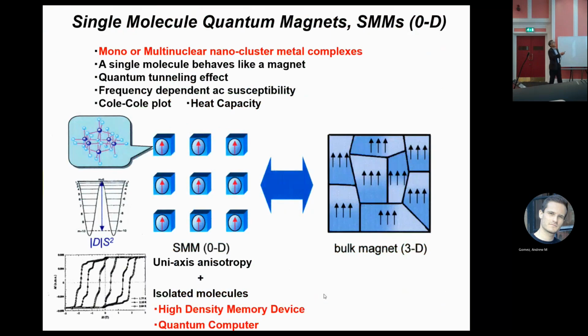So everybody knows the single molecule magnet. A classical magnet is a 3-dimensional ordering. So 3-dimensional ferro or ferrimagnet, 3-dimensional magnetic ordering. However, a single molecule magnet is 0-dimensional. It is composed of a mono- or multinuclear nanocluster metal complex. This molecule and other molecules have no interaction, isolated. And this has a double-well potential below the blocking temperature, upstream or downstream, frozen. So under the magnetization, upstream changes to downstream. On this occasion, we observe the hysteresis. So one molecule works as one magnet, works as one memory. Then this is available for high-density memory devices and also quantum computers.